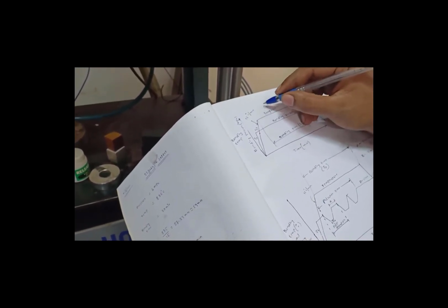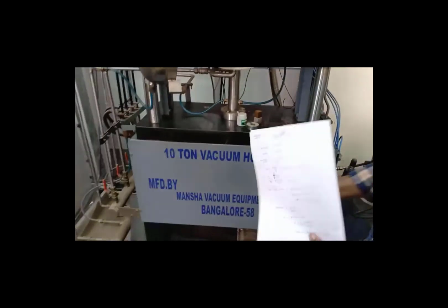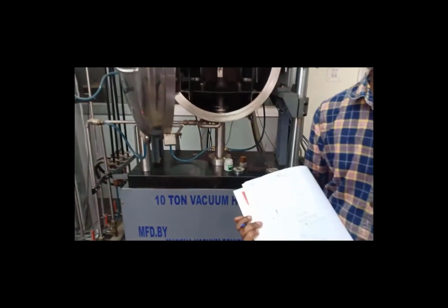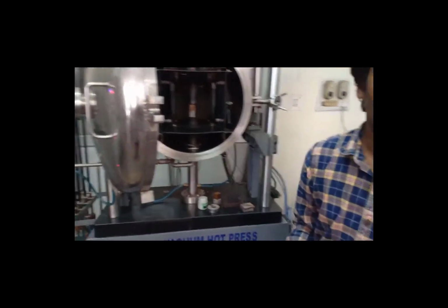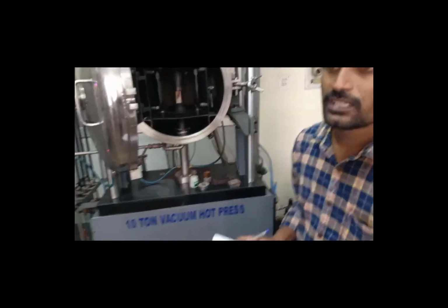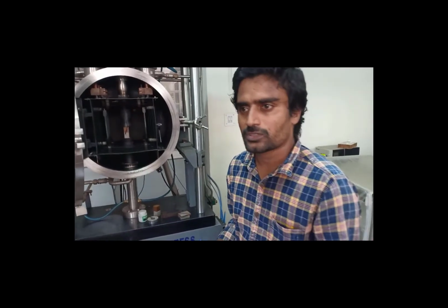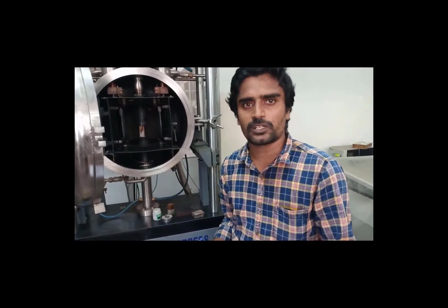Why am I taking two parameters, S2 and S3? S2 applies if you are going for any pulsation. Now I am not applying the pulsation here. S3 is for holding without any pulsation. If any material has an oxide layer, then to remove the oxide layer we require a pulsation. That depends on the material. Materials like aluminium and magnesium require the pulsation, while certain materials do not require the pulsation period.